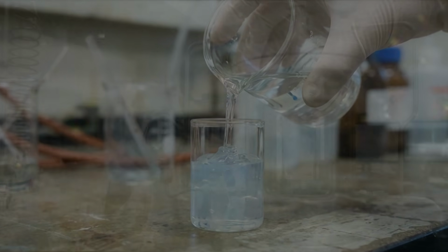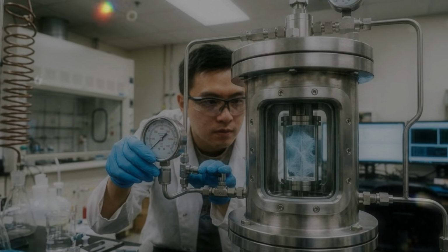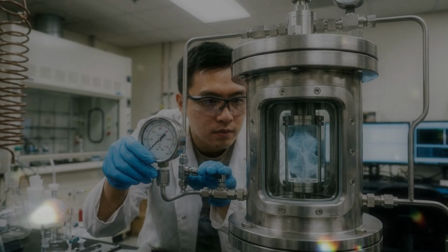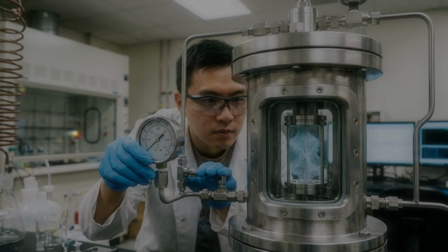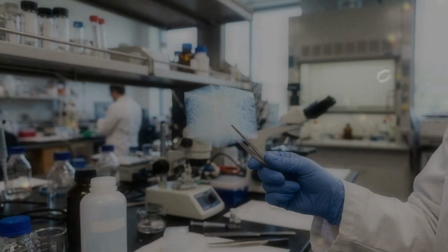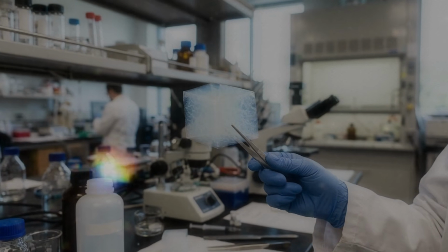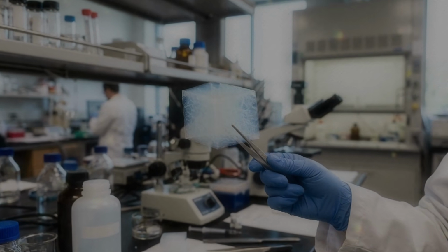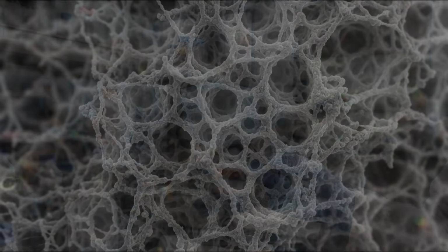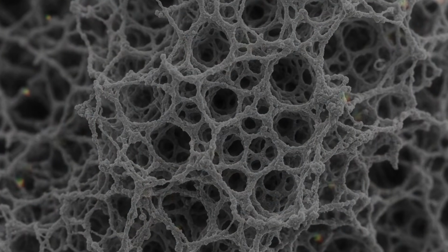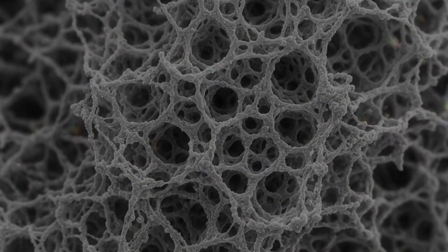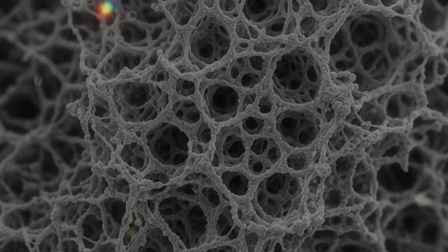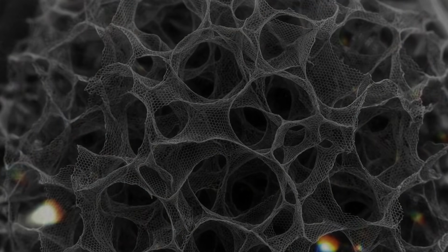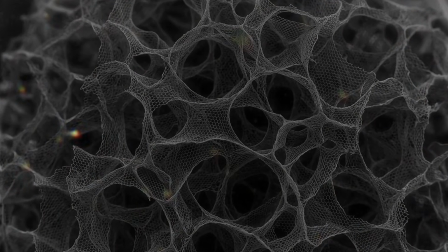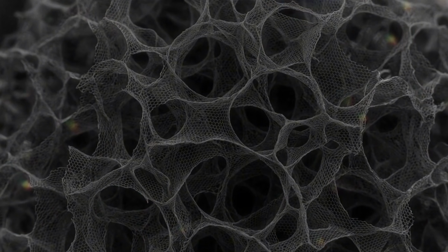Electrical conductivity follows a similar pattern. For current to move through the aerogel, the carbon sheets must form connected paths. If gaps interrupt those paths, conductivity falls. If the sheets contact each other well and have been processed to restore their carbon network, current can travel more easily. Compression may bring sheets closer together and change the electrical resistance. This allows some graphene aerogels to act as pressure or strain sensors.